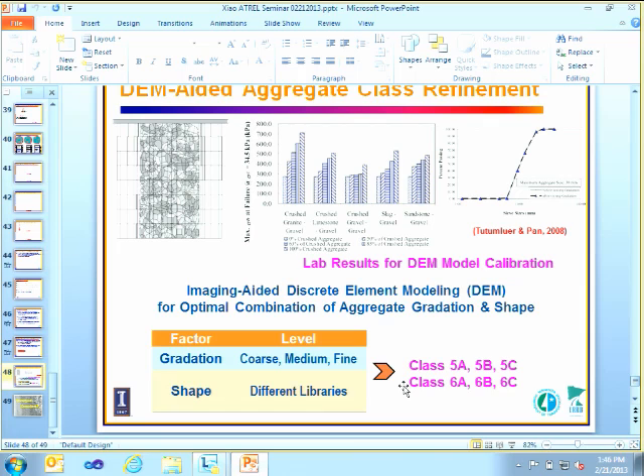I guess he's proposing just to modify the state specs. For example, whatever the limits are, if he's shooting for a gravel to sand ratio of 1.5, then the limits can be modified so that it always falls within that range. Yes, our intention was not to propose new gradations beyond the existing gradation band, because it's too risky for them to use gradations outside of it. Because they have a very wide gradation band, based on the aggregate shape properties we can come up with a gradation within this band to achieve the optimum shear strength. So we need a method to tell which gradation in that band will give me the optimum, if I have aggregate shape properties like uncrushed gravel or crushed stone.